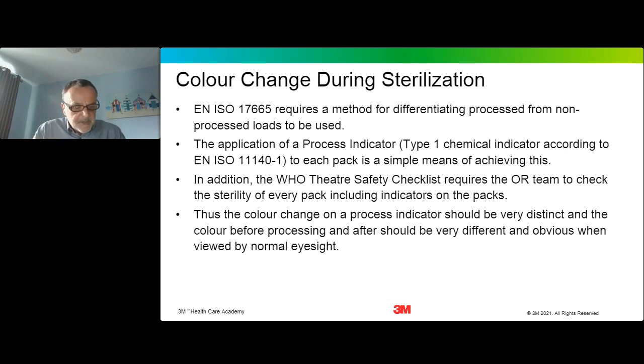Now, EN ISO 17665 requires, as I mentioned earlier, a method for differentiating processed from non-processed packs. And the application of a simple type 1 chemical indicator is an easy way for the hospital sterile processing department to achieve this. And in addition, I also mentioned that the OR teams, if they're using this surgical safety checklist, would use the tape as one of the indicators to judge that the pack is sterile. And it makes sense that the indicator colour change should be very distinct, unambiguous, and the start and end colours should be very different.